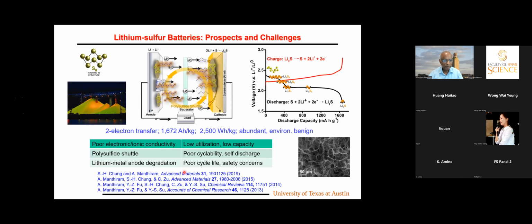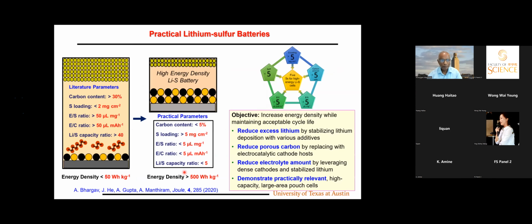More importantly, if you use sulfur, we have to use a lithium metal anode, and that leads to poor cycle life and safety concerns. So at least in the past, a lot of work has been done with very low sulfur loading, very high electrolyte amount, and a high amount of lithium as well. If you do these kinds of things, the practical energy density will be pathetically low, maybe less than 50 watt-hour per kilogram.